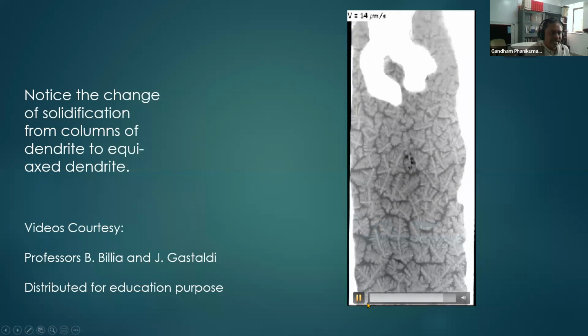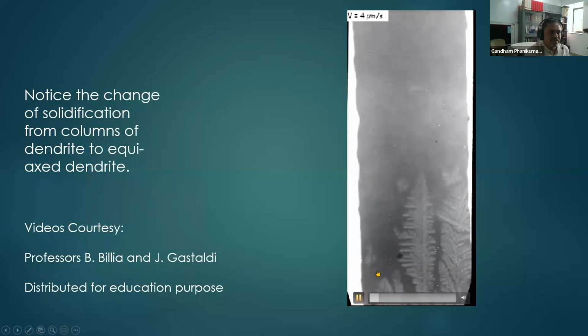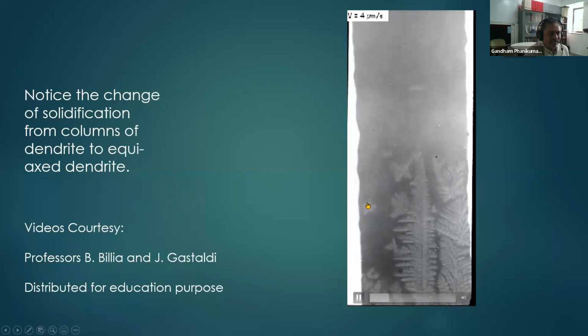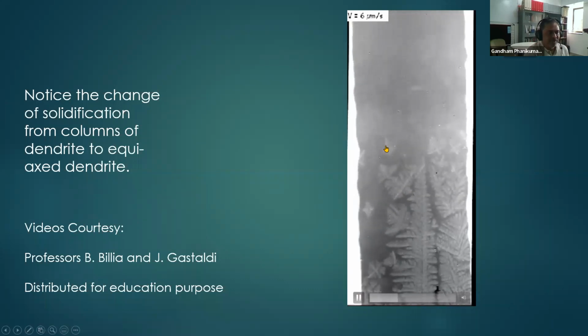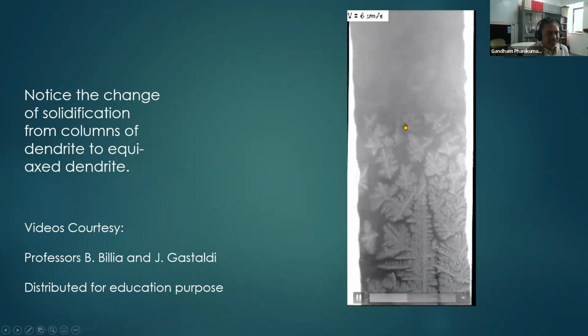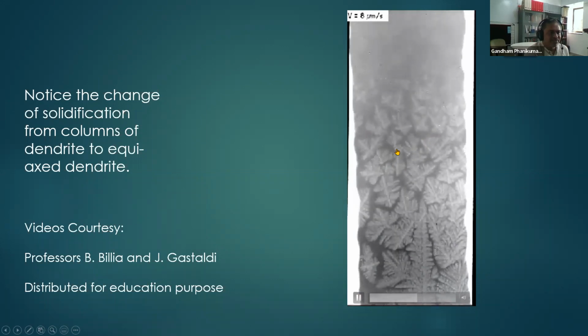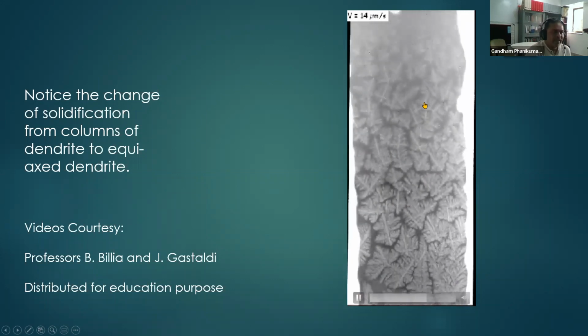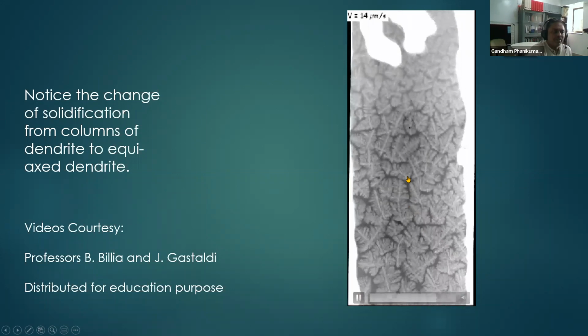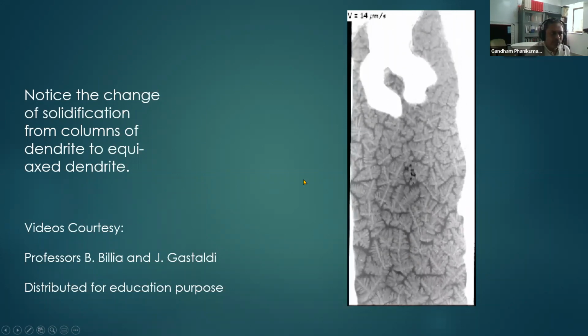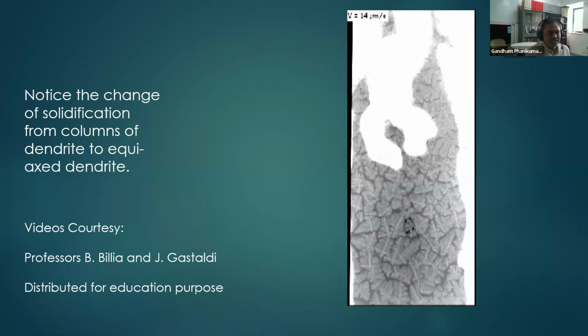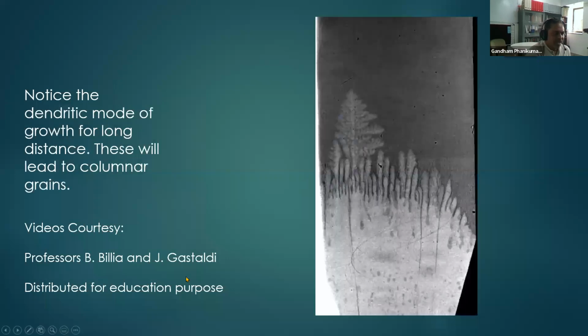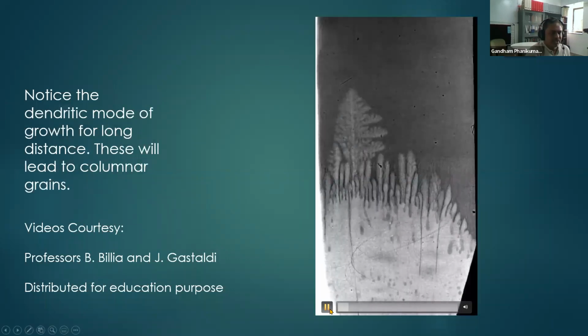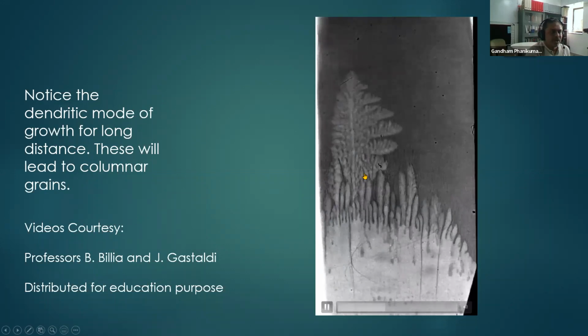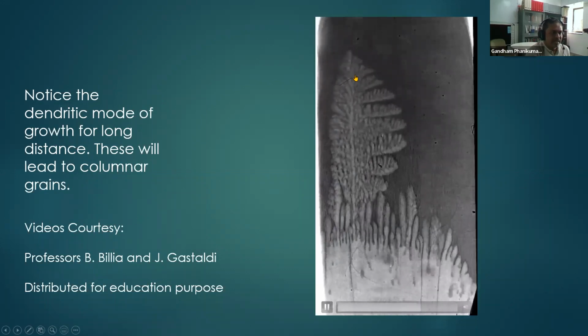So I will repeat this again, because this is quite a very important phenomenon. You can see that in the liquid, the solid is nucleating. And these are the equiaxed grains that are nucleating because there is enough driving force for that to happen. Okay, so that is also possible in additive manufacturing. If you go slow enough, you may have equiaxed growth that can take place. And here is again one more such illustration to show you how the dendritic growth is taking place.